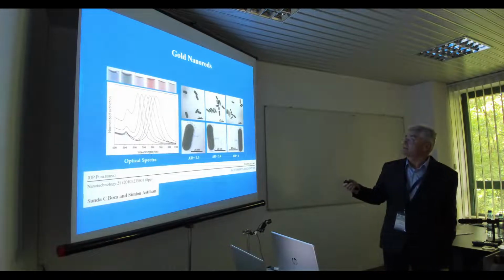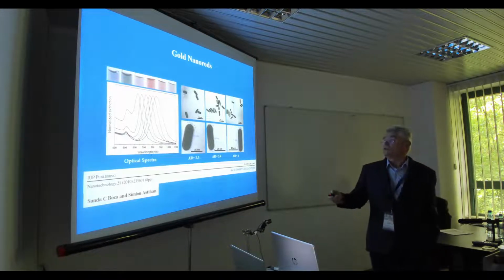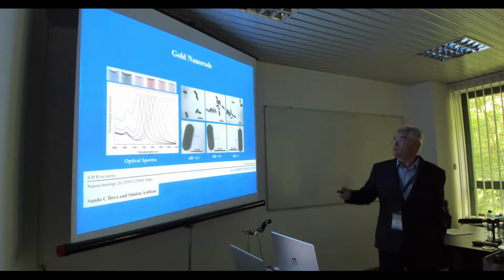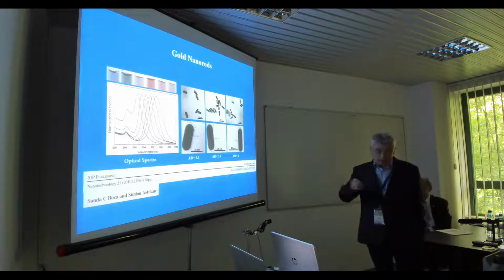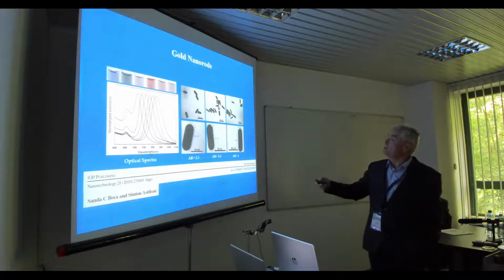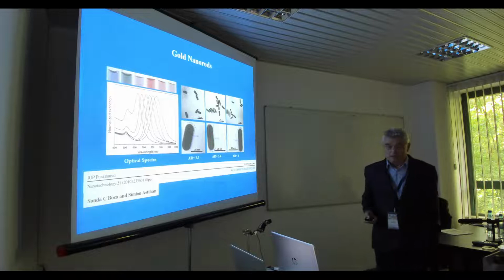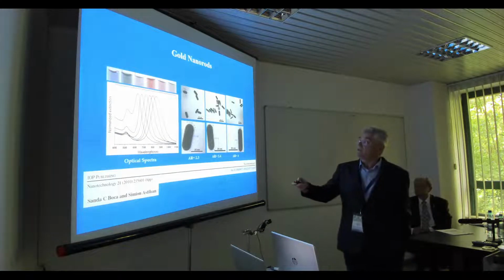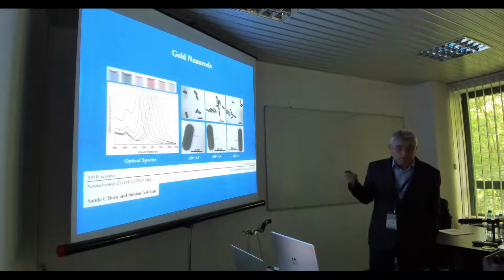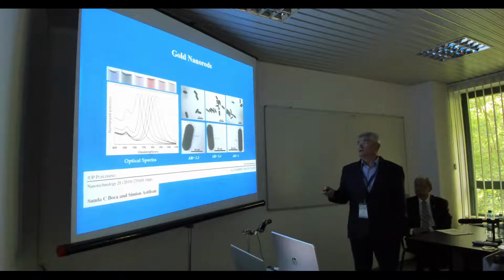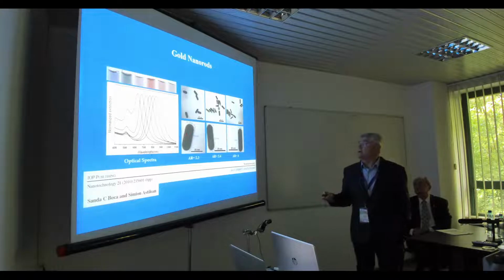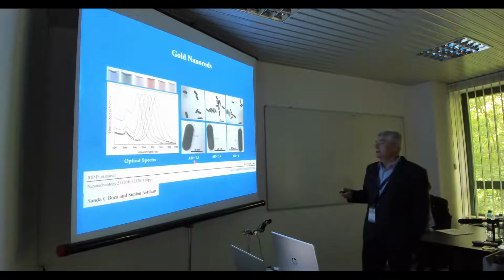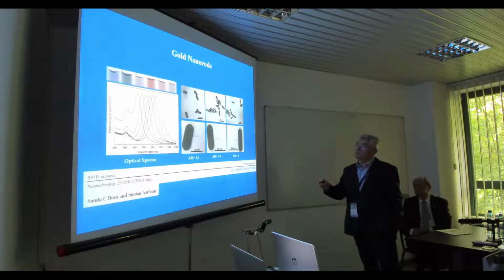One is transversal, located around 500 nanometers like a round shape, and the second resonance is longitudinal along the particle. So when you use unpolarized light, you will always get this kind of double resonance, which can be controlled very nicely by the length of the nanoparticle, and the aspect ratio shows very clearly.